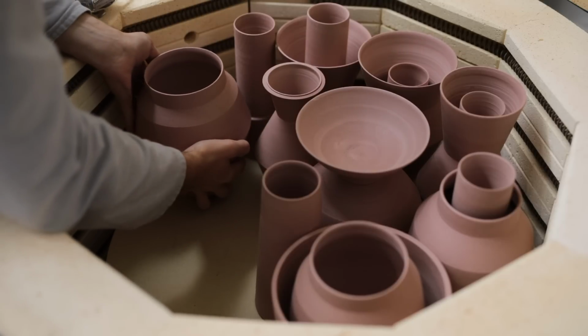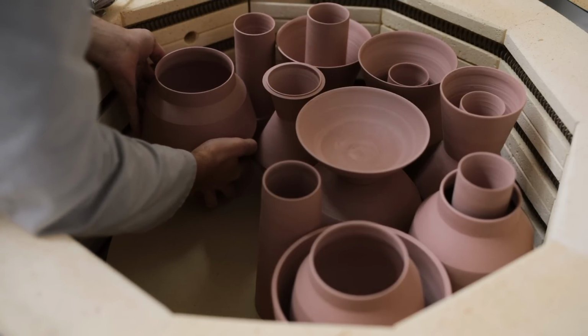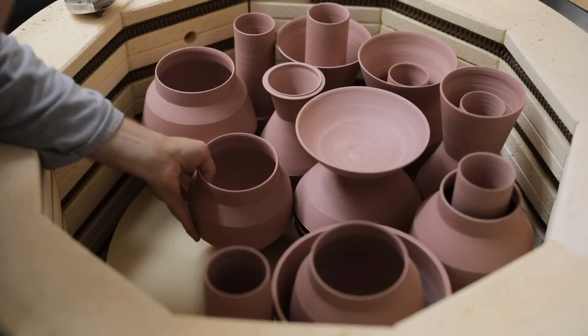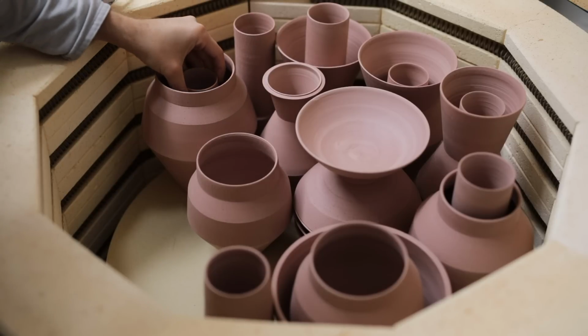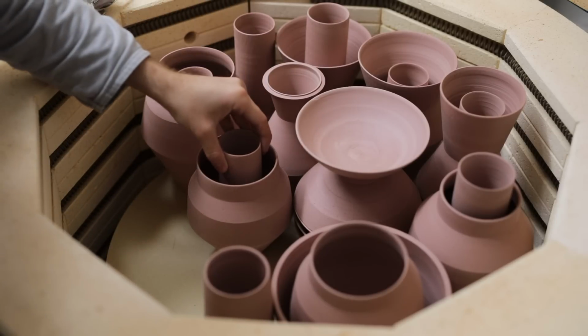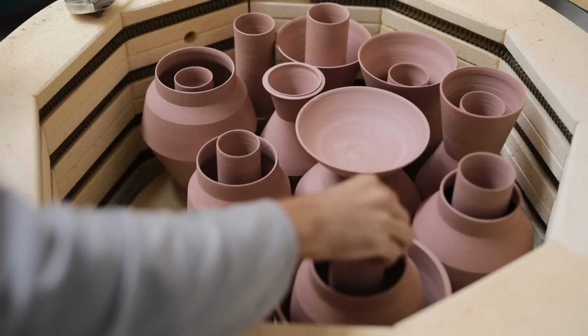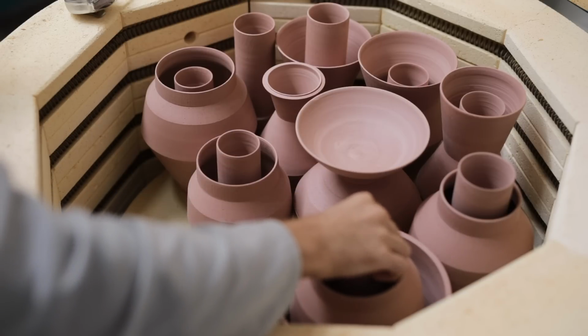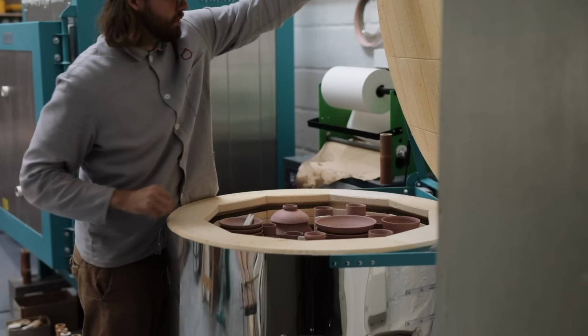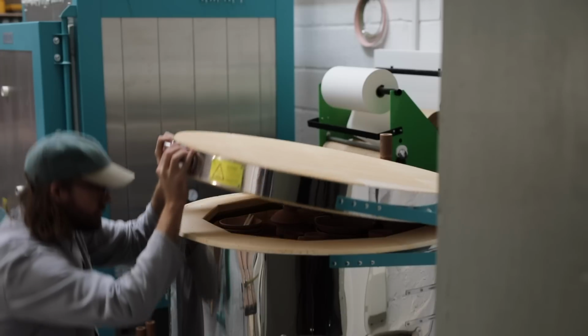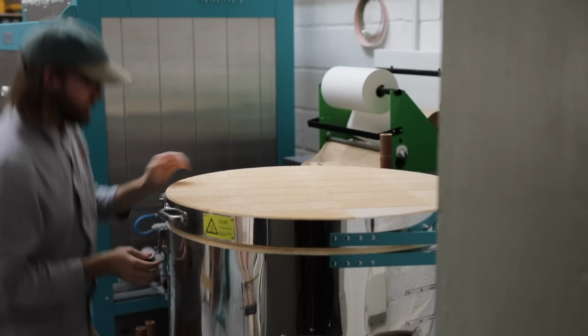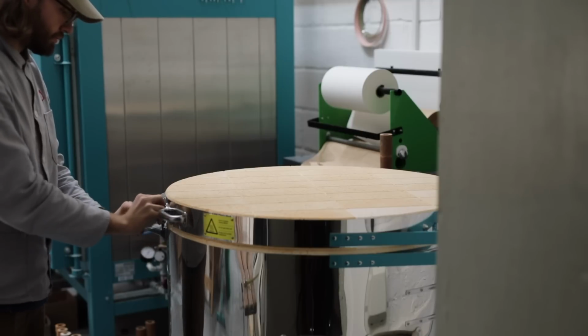You have to make sure that the pots are completely bone dry before you fire them, otherwise moisture can quickly turn to steam, which can cause pots to explode into thousands of fragments. I also try to pack each kiln as densely as possible, this way the firings are more cost efficient. I then close it carefully and watch to make sure that no pots sit up too proudly, as I obviously don't want the lid to crush them.